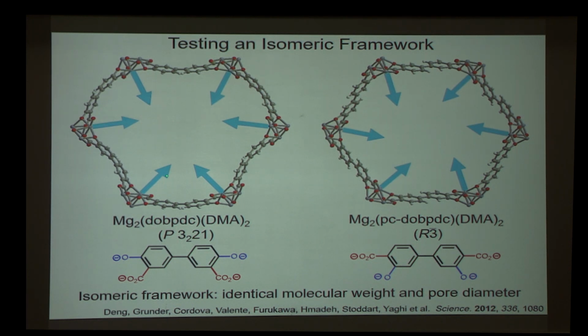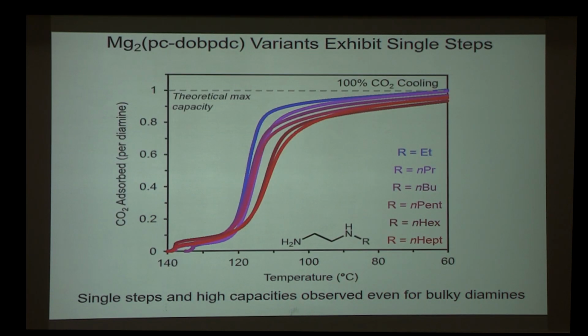In the parent framework, the metal sites point towards each other in pairs. But in the isomeric framework, there's a more symmetric distribution of the metal sites. So my hypothesis was that this could alleviate that steric crowding. And indeed, this was successful. Now, using even the largest dangling alkyl group, as big as an N-heptyl, yielded a single adsorption step.